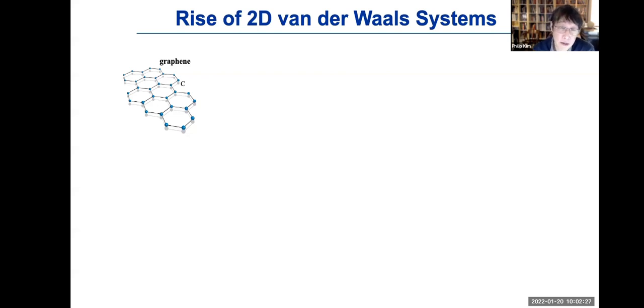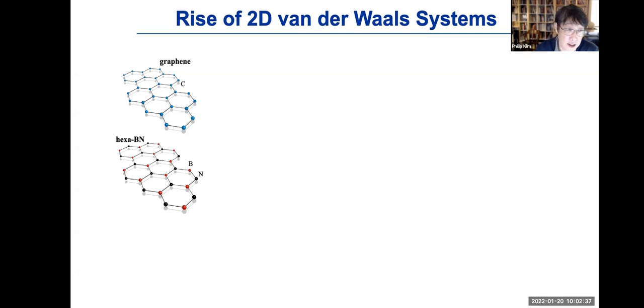Over the past 15 years or so, the community discovered more examples of 2D materials. Right after graphene, similarly, there's hexagonal boron nitride. It's a layered crystal of a hexagonal arrangement of boron and nitrogen. Again, the weak van der Waals force holds the layers together, and you can break these materials down to a monoatomic layer. Unlike graphene, which is a Dirac material with a linear dispersion relation, hexagonal boron nitride is known to be a very good insulator or semiconductor dielectric.